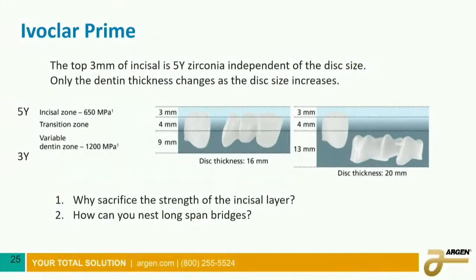Now Ivoclar took a very different approach. They put a 5Y zirconia on the incisal layer, but they kept the size of the incisal layer the same, independent of the thickness of the disc. And we were very concerned about that. We were very curious about that because they only varied the dentin zone here, or the gingival layer.